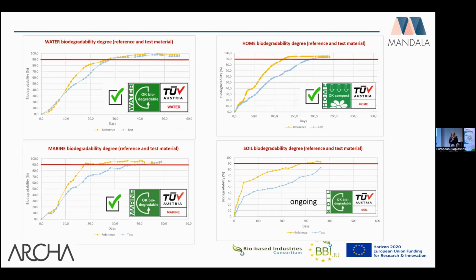We also performed some preliminary tests on the 4 different environments that we can apply on this plastic material to verify its biodegradability. We performed the test in fresh water, and we achieved 93–94% after 56 days for the preliminary formulation. As you remember from Marta's presentation, we used an adhesive, but we didn't test this adhesive in the formulation.